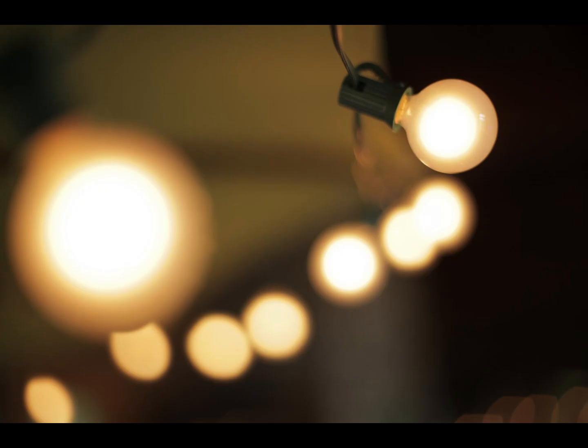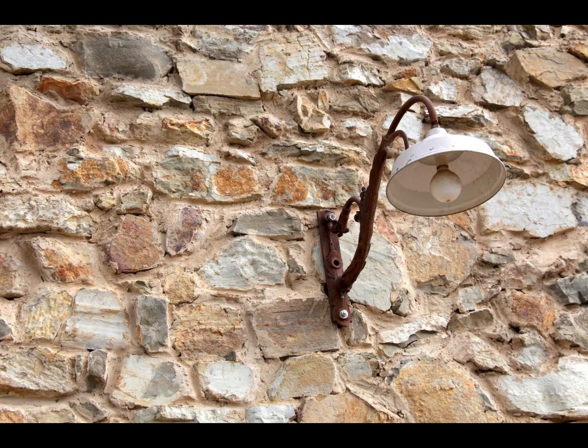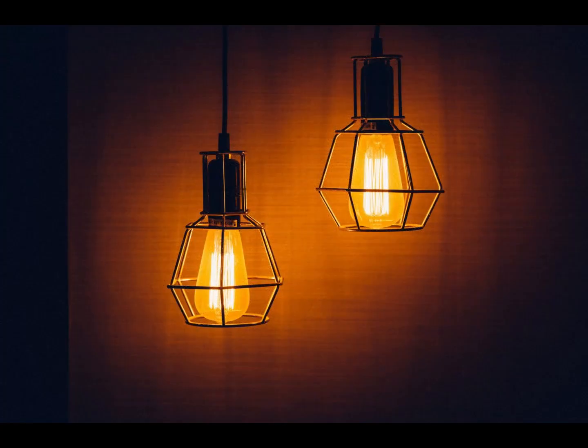Filament notching is due to uneven evaporation of the filament. Small variations in resistivity along the filament cause hot spots to form at points of higher resistivity. A variation of diameter of only 1% will cause a 25% reduction in service life. Since filament resistance is highly temperature dependent, spots with higher temperature will have higher resistance, causing them to dissipate more energy, making them hotter, a positive feedback loop. These hot spots evaporate faster than the rest of the filament, permanently increasing the resistance at that point. The process ends in the familiar tiny gap in an otherwise healthy-looking filament.